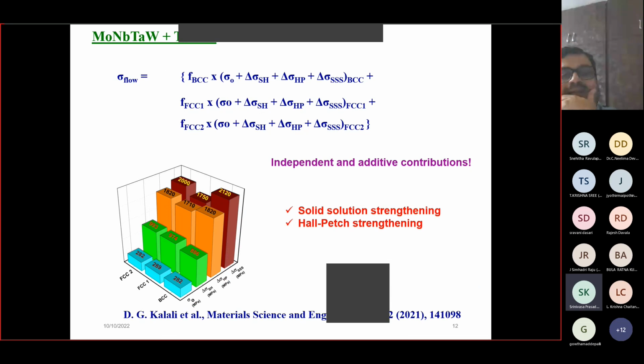And again, like the way we have done for the other systems, which is aluminum, cobalt, chromium, copper, iron, and nickel, in this also we figured out that several mechanisms involving lattice frictional stress, strain hardening, Hall-Petch strengthening, and solid solution strengthening, coming from various phases of this material, when we assume them to be operating as independent as well as additive contributions, it works very well.